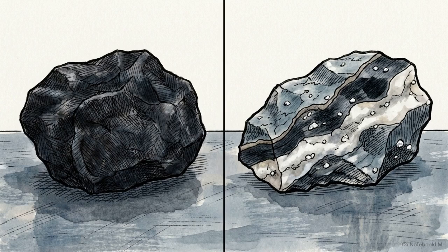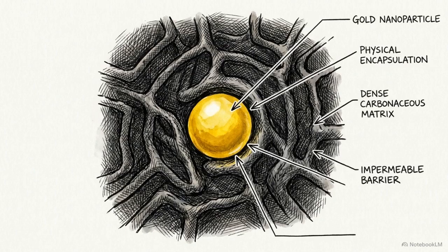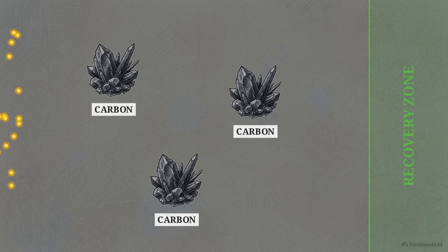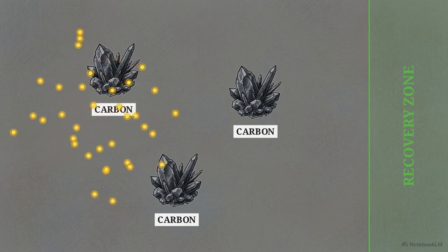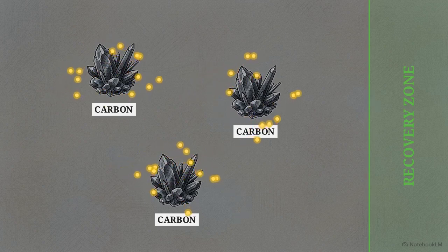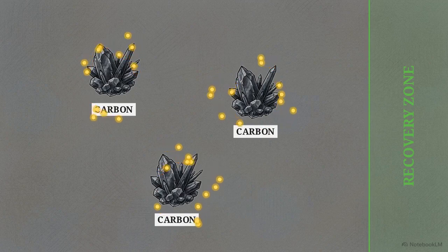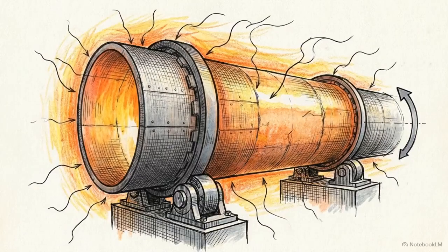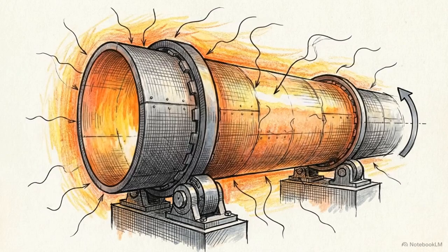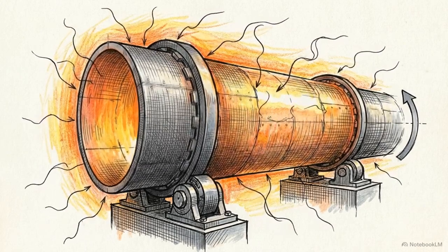The most severe operational challenge comes from refractory ores, specifically carbonaceous and telluride deposits. In these rocks, the gold is locked away at a microscopic level. Carbonaceous ores present a threat called preg-robbing. Natural carbon sabotages extraction by pulling dissolved gold away from recovery and locking it into waste. To counter this, operators insert an oxidative pretreatment. This thermal wave destroys the carbon, releasing the gold for capture. Thermal pretreatment represents the highest upfront capital requirement and the steepest ongoing energy demand in modern mineral processing.